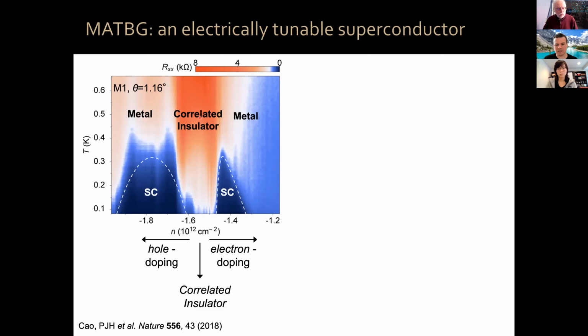So, in magic angle graphene, we can measure the resistivity versus temperature and charge density. We can vary continuously the charge density electrostatically, because our magic angle graphene is one plate of a parallel plate capacitor with another metallic plate. We can apply a voltage to vary the charge density in our plates. Okay, so we can vary the charge density continuously, and at a filling of 2 holes per moiré unit cell, we found a correlated insulator state. If we add extra holes, we find a superconducting dome. If we add electrons, we have a superconducting dome.